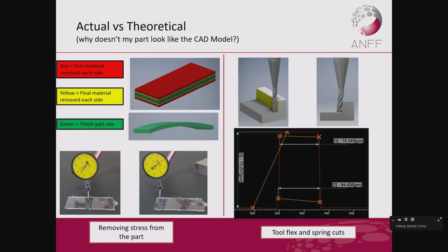We also have, when you're cutting and you've got a cutting tool in a large machine, and the machine might weigh anything up to 8 or 12 tons, you've got one piece of machine moving against another piece of machine, there's material and there's a tool there. Something often has to give. And if you've got a small, thin tool, or even the large half-inch ones, they'll still flex away a little bit from the material, and the ends might start to wear a little bit. So on this 75 micron high feature that we've got here, you can see the red outline. There's a 5 micron difference between the top and the bottom. So we've got a 2.5 micron wall taper, which is natural, a little bit like the ablation that Ben talked about yesterday, where the laser sort of induces this angle. We see it on a smaller scale here, but it's still a problem.